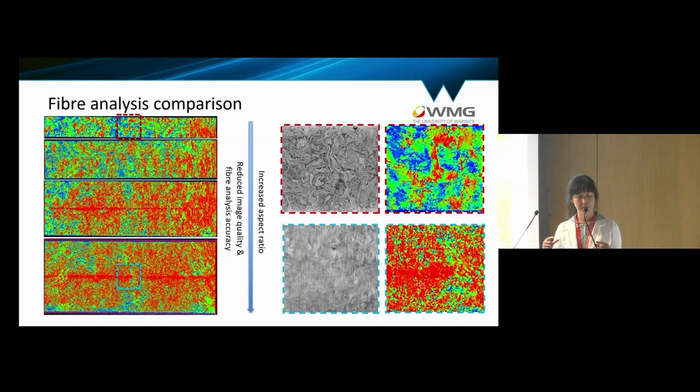If you remember the 4 different samples we've scanned, they have widths of 25 mil all the way up to 100 mil. And as you would probably expect, as we increase the sample width, we are seeing decreased image quality, especially for the very wide sample. We are seeing these artificial stretch marks on the image surface due to streaking artifacts.